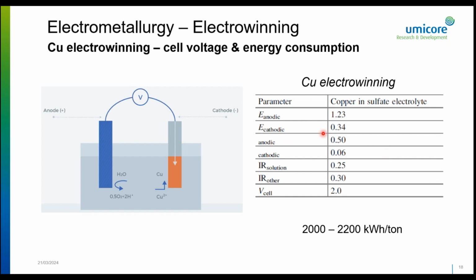additions, and these have to do with resistances of the system. So you have overpotentials at the cathode and at the anode. You have a resistance of the solution. You have other resistances, and these all accumulate into the cell voltage. So unfortunately, you cannot work at the thermodynamic or theoretical potential, and then you arrive at this specific energy consumption for copper electrowinning.